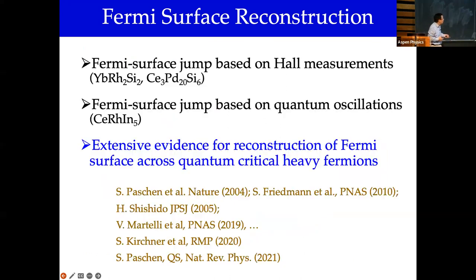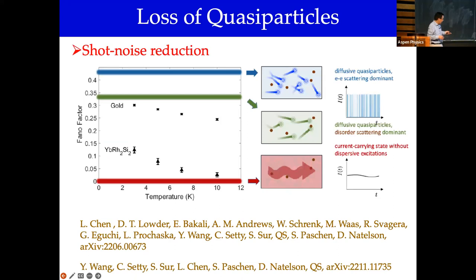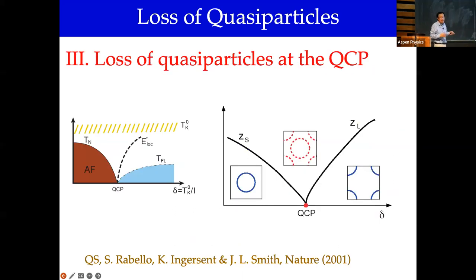in the low temperature limit. And so there was a massive amount of experimental effort to look for the Fermi surface jump. And by now, there's quite extensive evidence within this class of correlated materials that across a quantum critical point, the Fermi surface experiences a jump. The initial experiment was done by Dresden, Silke Paschen, and collaborators in these materials. Condensed matter physicists love quantum oscillations, the gold standard of measuring Fermi surfaces, which has also provided evidence for a jump of the Fermi surface when the tuning parameter conditions are suitable. And in other materials as well. So that raises the question: how could it be that the phase transition is continuous, yet something is jumping? The Fermi surface would be jumping. How could that be possible?